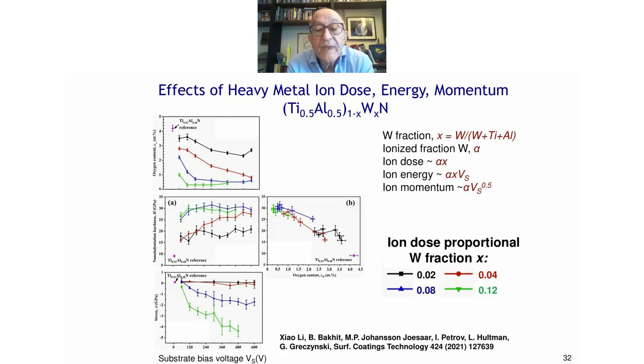And then the ion energy is proportional to X and the voltage applied, while the momentum is proportional to X times the square root of the voltage. That's missing in this slide. And here we varied the X by keeping the peak current the same, but we varied the length of the pulse from 20 microseconds, to produce X of 0.02, to 100 microseconds pulse length. Of course, that increased the power of the HiPIMS pulse. And then we get the green curves, which is 0.12.